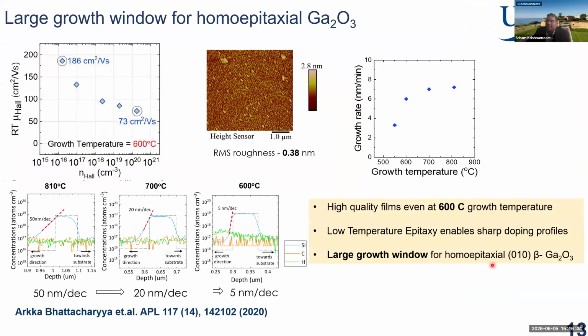The first thing that's interesting that we observed in the MOCVD growth of gallium oxide is that the growth window is fairly large. Gallium nitride needs at least about 1000 C and higher to crack the ammonia precursor and to have sufficient adatom mobility on the surface. Whereas here, high quality gallium oxide can be grown even at temperatures as low as 600 C. And this is experimentally measured Hall data as a function of electron concentration from Hall measurements. We can maintain smooth surface morphology and a very sharp doping profile when we grow colder.